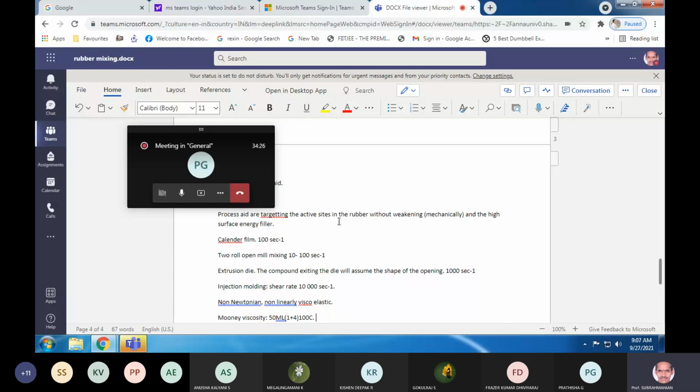In case of the polychloroprene rubber, we said W type. W type is the mercaptan modified, and you have a peptizable sulfur modified, the G type, which is non-crystallizable, very important. Non-crystallizable means even at a low temperature, it may not become stiffer. Of course, it is limited by the Tg; up to the Tg, there is no question of stiffening.